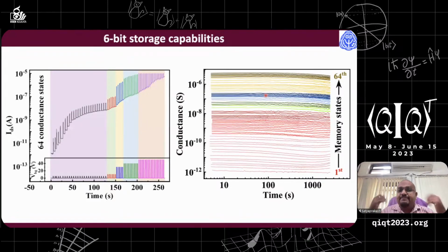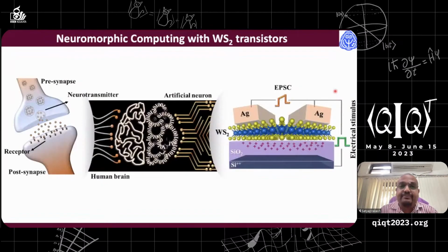We have achieved a 6-bit storage capability. What I mean by that? That means when we apply a different pulse train, say we have applied 5 volt, 10 volt, 20, 40, and 50 volt over here, and you can see here there is a consistent change in the conductivity of the system. Once you achieve each conductivity, you can see how long this conductivity can stay. We have done it for more than 1,000 seconds for each conductance state, and we were able to achieve 64 memory states, which is quite impressive.